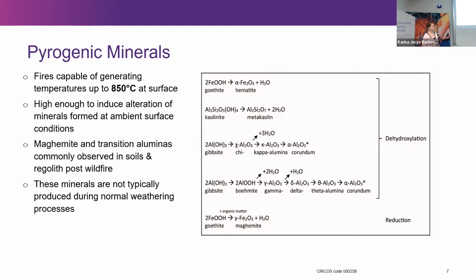And if there's organic matter in the mix, what we get is a sort of partially reducing environment. And then we can form a mineral called maghemite, which is a partially reduced iron oxide. Maghemite is magnetic, so it's really easy to identify in the field. You can just pick it up with a hand magnet. So these minerals are not typically formed during surficial processes. If we identify things like maghemite and transition aluminas in our soil or regolith, then we might start to say, hey, there's been a fire here that's affected this.